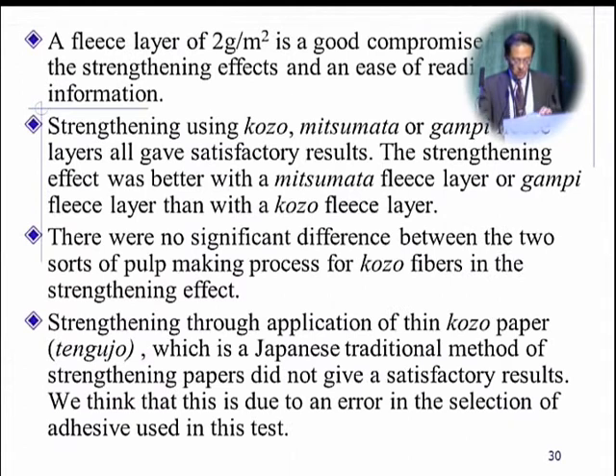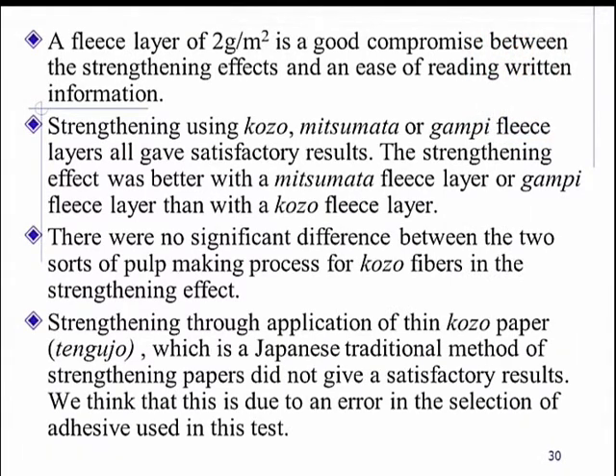Conclusion. The results show that a fleece layer of 2 grams is a good compromise between strength effects and ease of reading written information. Strengthening using kozo, mitsumata and gampi fleece layers all gave satisfactory results. The strength effect was better with a mitsumata fleece layer or a gampi fleece layer than with a kozo fleece layer.